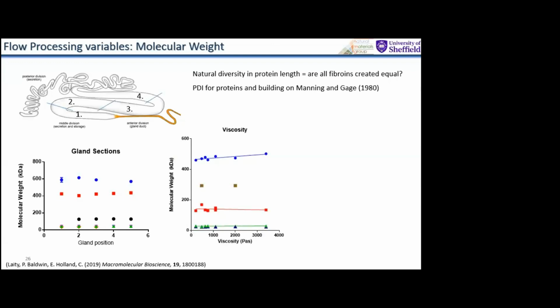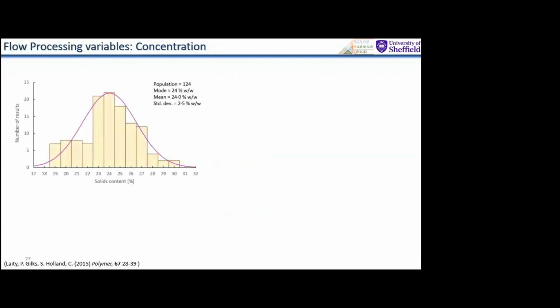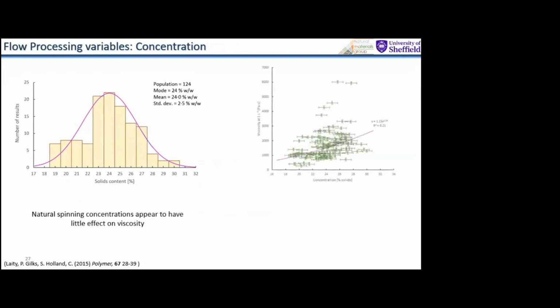What we found with this is that there's variation in the silk's mechanical properties, but it's nothing to do with the length of the protein. So the other thing that a polymer scientist would say is, oh, the concentration, it's the amount of proteins that we have in the gel that will affect its mechanical properties. And we see this huge variation, about 15% in terms of solids concentration, but we find that natural spinning concentrations apparently have very, very little effect.